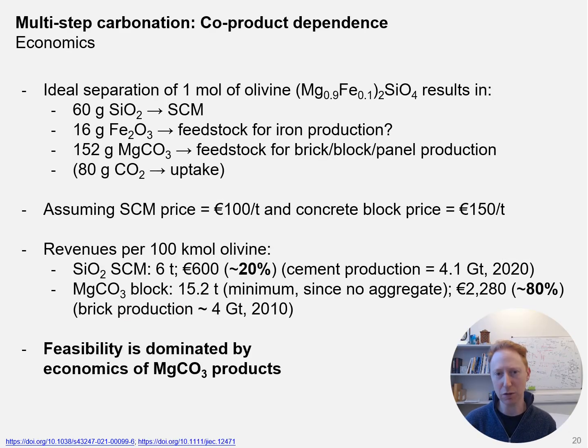Now let's take a deeper look at the multi-step carbonation process, taking the olivine case on the previous slide as an example. From olivine, we can produce three products: a silica-rich supplementary cementitious material, an iron-rich oxide, and a magnesium carbonate product, which can be used as a brick or a block. The CO₂ that is mineralized in this process is bound in the magnesium carbonate product. The silica supplementary cementitious material is highly reactive, perhaps better or more reactive than ground granulated blast furnace slag and comparable to silica fume. Since silicon and magnesium are the main elements in olivine, let's consider them further here.